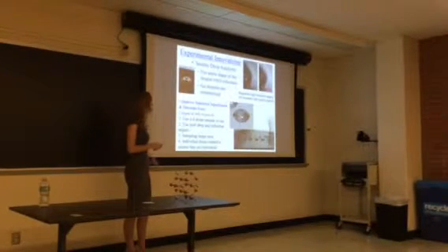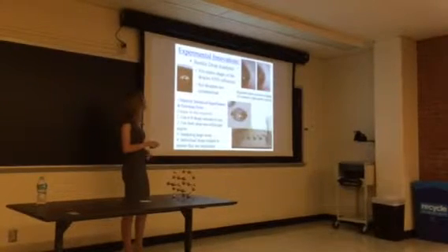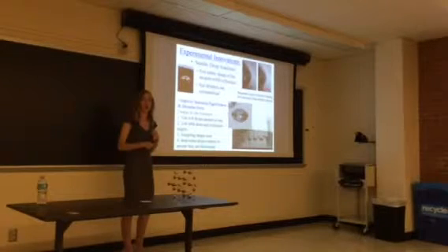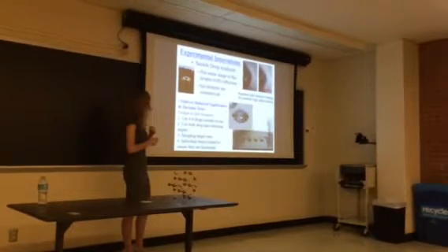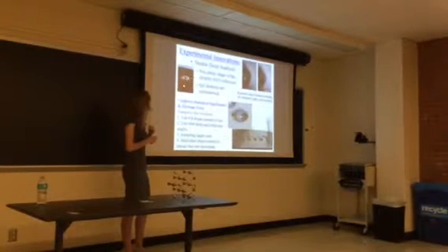The experimental innovations we made to separate our work from others were to use regulated high-resolution imaging for consistent and high-quality analysis. Also, we did not use tangent lines in order to determine our contact angles. We used sessile drop analysis, in which we modeled this as the top of an ellipse, and then fit an ellipse to both the droplet and the reflection, and then used the dimensions of that in order to determine our contact angle.